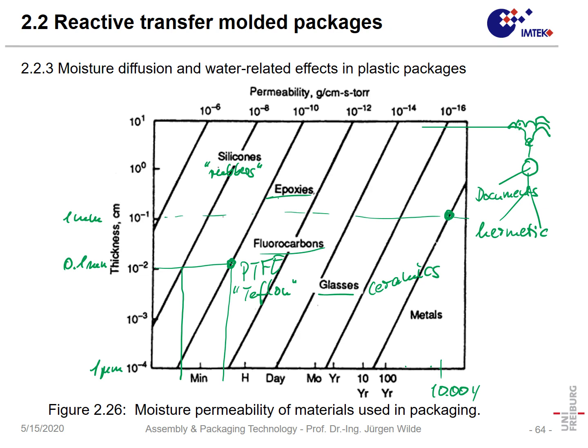And the reason is silicones are hydrophobic, and if you have liquid water, it just drops off. Yeah? So that means on silicones you will not have standing water, but due to the high surface energy, the water will pearl off and it will run away due to gravity. And on the other hand, for instance, if you have electronics going under the dew point, you have precipitation of water, but you have the water not on metal parts, but you have it on the protective layer of the silicone. And again, here it can pearl off. And in that way, silicones are not protecting against diffusion, but they are just protecting against liquid water running into something. So that's very important.